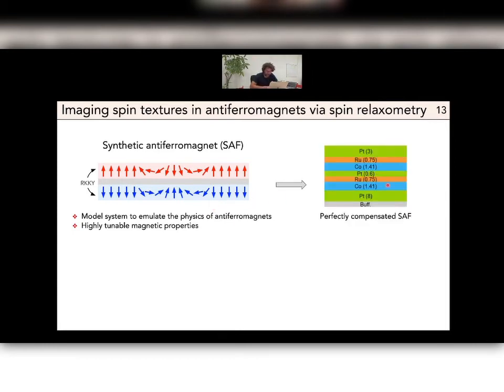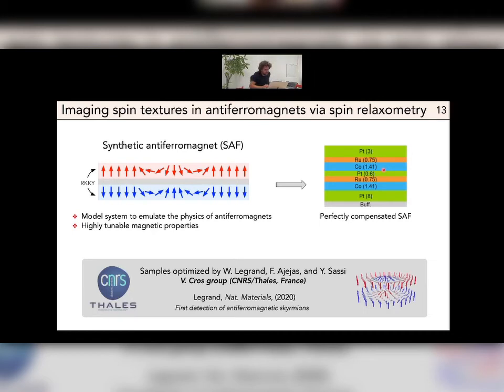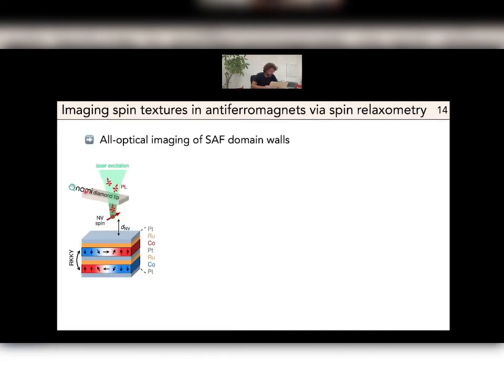So in our case, we use two cobalt layers here with ruthenium and platinum, and we use a perfectly compensated synthetic antiferromagnet, meaning that the thickness of the two cobalt layers, which are the ferromagnetic layers, is exactly the same. So this sample has been optimized in the group of Vincent at CNRS Thales, and this sample led to the first detection of antiferromagnetic skyrmions. So we started with a sample in which the thickness of the cobalt layer was chosen to have out-of-plane magnetic anisotropy, and we decided to use our NV magnetometry to try to image domain walls in this sample.